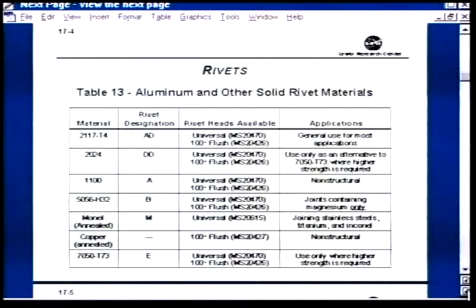1100 aluminum, that's usually non-structural. A 5056 is a special one in this respect. They're still used. Some people are not aware, I don't think, that they are stress corrosion sensitive, and they really should not be used in anything other than a magnesium joint, where magnesium is more stress corrosion sensitive than the 5056, so therefore the 5056 will work out better.